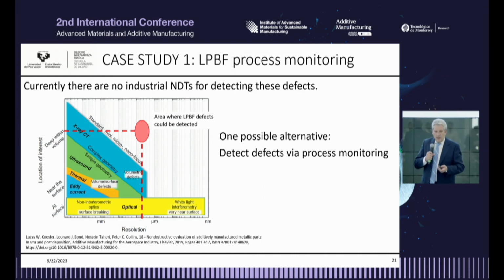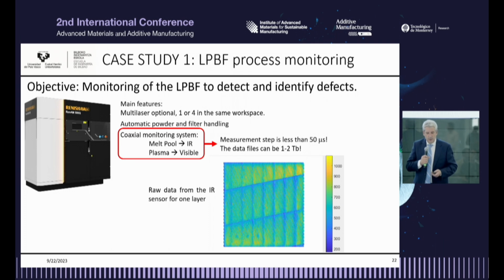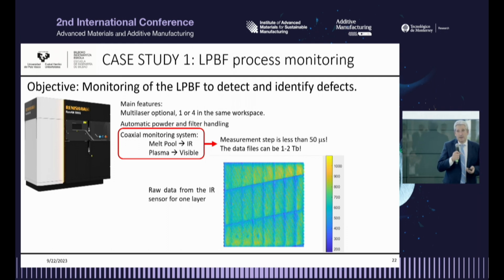Okay, so in that case, we have a system with a monitoring of the process. We have two different sensors. One of them measures the radiation on the infrared level, somehow related with the melt pool, and another sensor measures the visible wavelengths, somehow related with the plasma formation, which leads to defects. And we obtain a measurement in less than 50 microseconds, which is good news in principle. But the bad news is that for each part, and not really big parts, we obtain files from 1 to 2 terabytes. So the amount of data is huge.